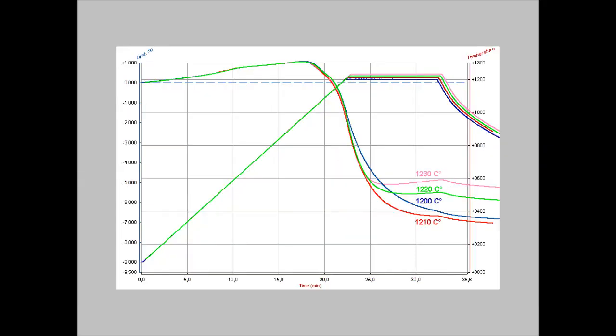The result of the test can be confirmed by running several trials at slightly different temperatures. In the shown example, it is quite obvious that the best sintering conditions are achieved at 1210 degrees, since we get the maximum shrinkage and the sintering curve becomes perfectly flat. Rising the temperature up to 1220 or 1230 degrees, the material starts swelling, the shrinkage becomes lower, and the sintering curve inverts the slope.